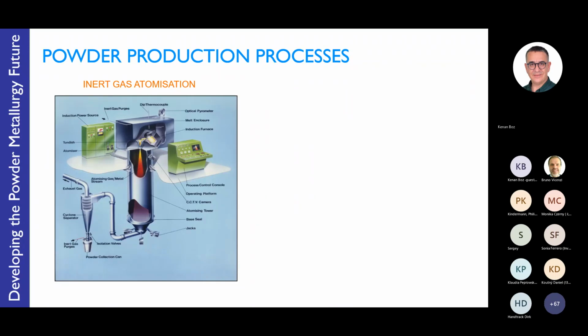So the atomization occurs in this enclosed vertical chamber, which is often water cooled, and the gas to metal flow rates are balanced to optimize the performance and efficiency of the equipment. By the time the powder particles, which break up under the pressure of the gas, reach the bottom of the chamber, they've typically solidified with relatively fast cooling, but still slow enough to form a spherical shape. And then the gases and the particles are separated in a cyclone, where the gases are exhausted and the powder particles are collected. This does allow the configuration to have recycling of the gases, and for argon that sometimes is justified in terms of the capital equipment investment.